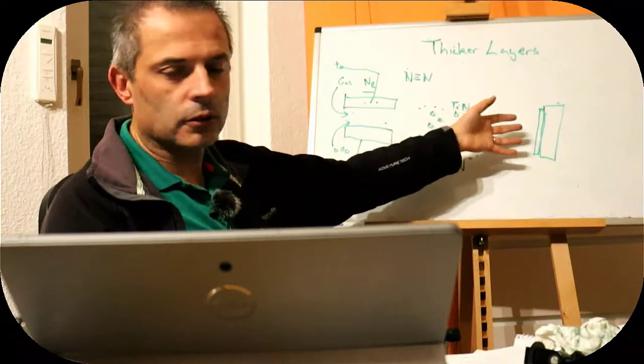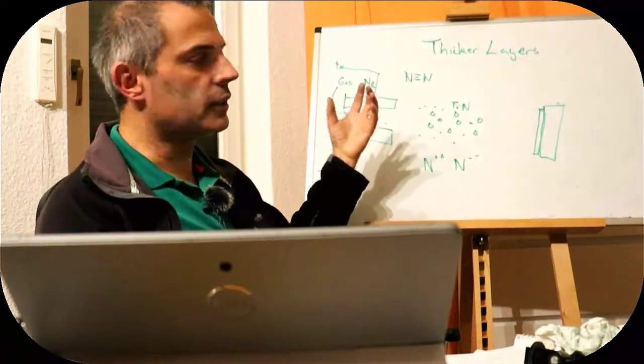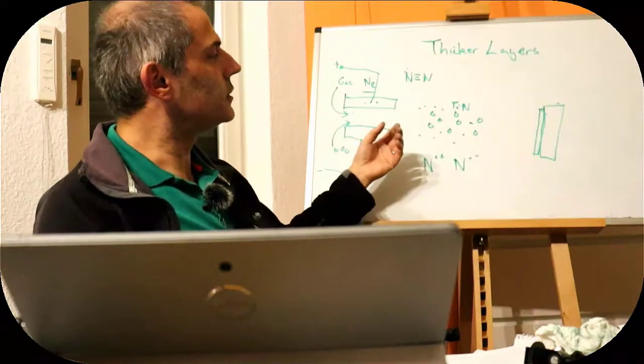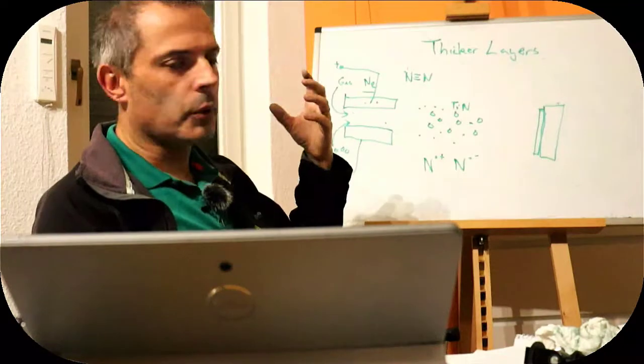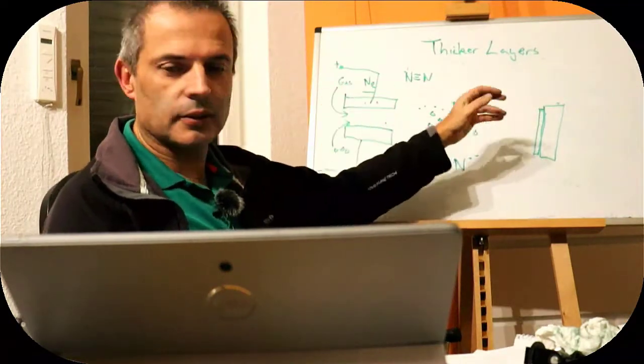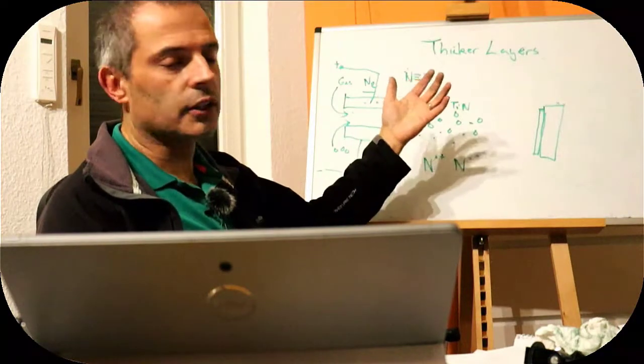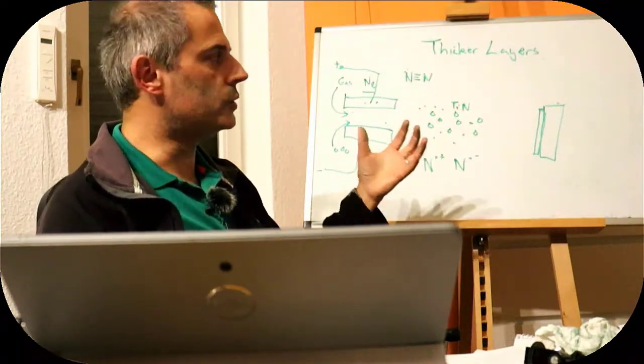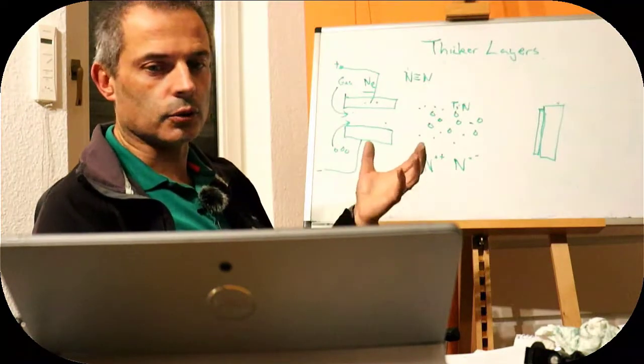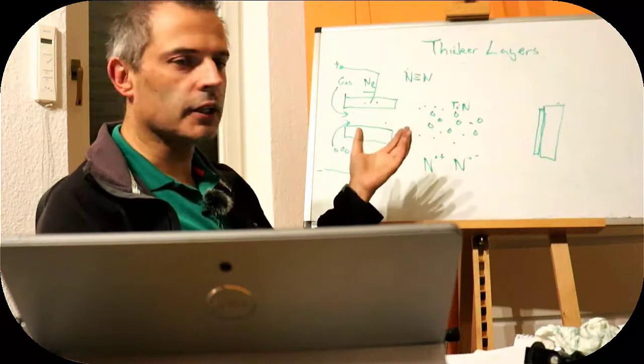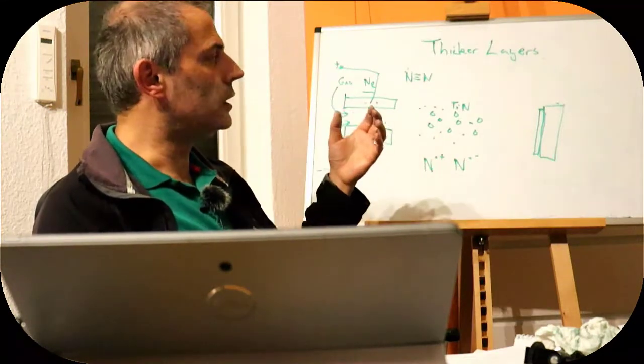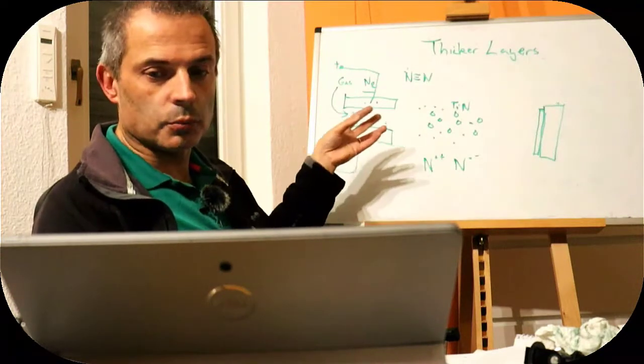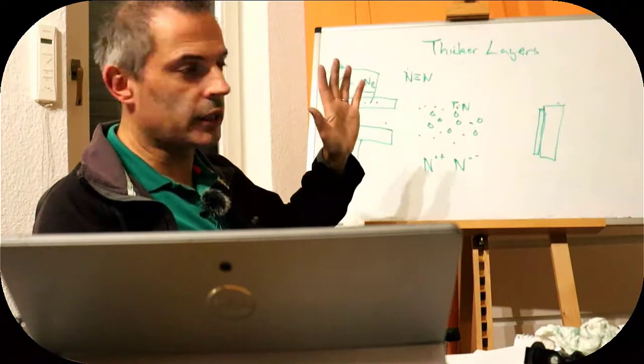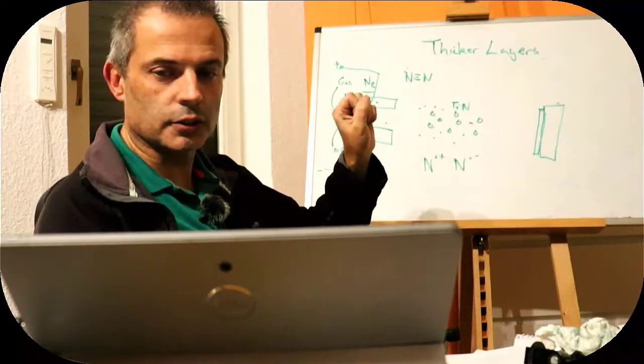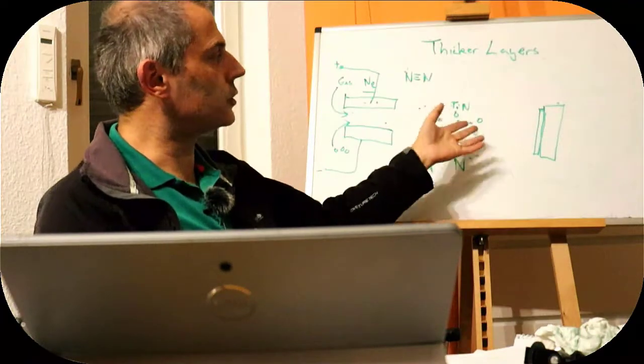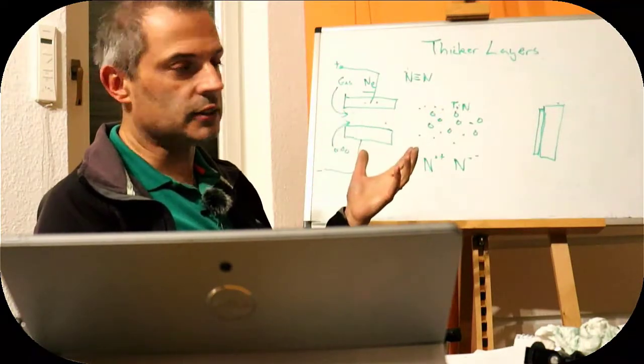Because particles are coming along, the film is going to build up a lot quicker than if we were going to put it down atom by atom, and so we can generate relatively thick films. But one of the problems is that the splats, as they hit, cool relatively quickly, and so they can often generate quite porous coatings, which can be good. So the insulation for turbine blades is typically made this way. The insulation for turbine blades for aero engines, for example, is zirconium dioxide, which is applied in this way, and the pancake splats, each particle goes on, crashes, flattens and solidifies, and as long as we're far enough away from the heat source, it stays as it is.